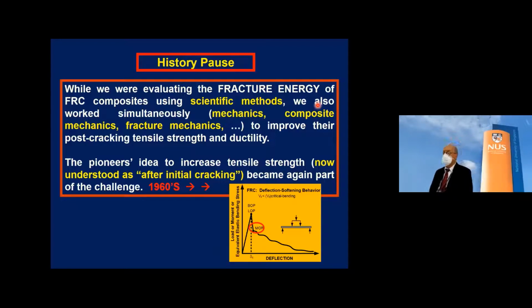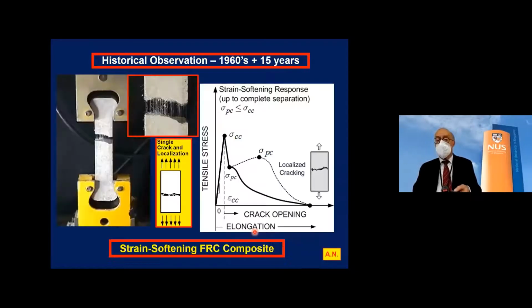So the pioneering idea to increase tensile strength is now understood after initial cracking. The first pioneers simply looked at the cracking strength, and that didn't change very much when you put 0.5% fiber or 1% or 2% fiber. But after initial cracking, that was the key. They didn't understand it, but now we understand it. And so after this initial cracking, we get something, I call this the maximum post-cracking stress in a tensile test, or the modulus of rupture in a bending test. That became understood and the best part.